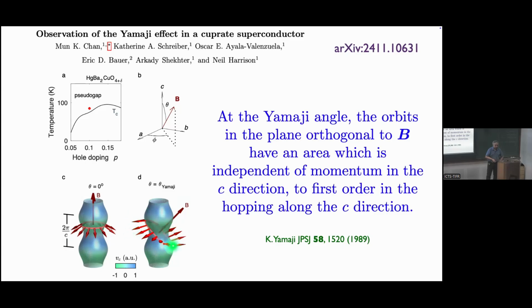And various things depend upon the area of that orbit, as you learn in semi-classical physics, as shown by Onsager. What you find is that for a certain angle, called the Yamaji angle, to first order in the corrugation of the Fermi surface, the area doesn't change. So if you slide in the C direction, the area of this orbit orthogonal to the magnetic field only changes to second order in the warping. It's unchanged. So this means that there's no dispersion along the C axis. It's a flat band. So at certain angles, you get a flat band, just like a Landau level.